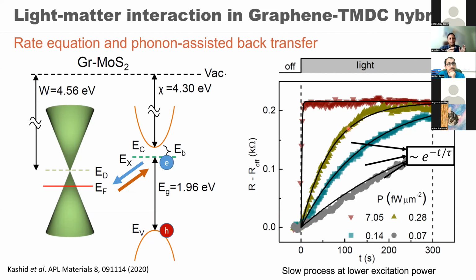But I think the best region of responsivity per se is in the order of 40, 50 Kelvin to about 200 Kelvin. After that, the phonons become really active, and as soon as the electrons get transferred, the phonons start transferring them back into the chalcogen layer. And again, the responsivity starts coming down. Okay, so there's an optimal temperature range that is important.